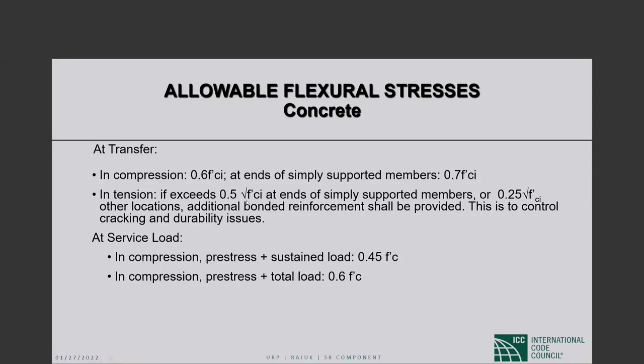Now, typically I've been finding from my practice that this value, the F prime C and FC, these are the as-built, whatever you get from as-built. For example, if they give you a value in the as-built, you'll find out that if you do the testing cylinder, they're typically quite a bit more, which is a good thing. Typically, we have been finding that the actual cylinder strength is about 30% more.